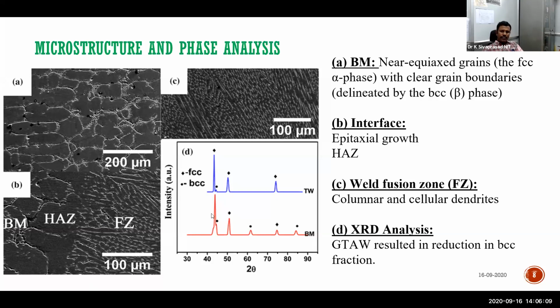And when we have seen this base metal and TIG weld, in the base metal some traces of BCC phase were there, because in Al 0.5 a significant BCC phase was there. But when we have done TIG welding, similar welding, we were surprised to note that in the fusion zone the BCC phase was dissolved. We got a single phase FCC. In fact, single phase FCC is an advantage from a mechanical point of view. After seeing the XRD itself, we felt that our weld is supposed to give good properties.